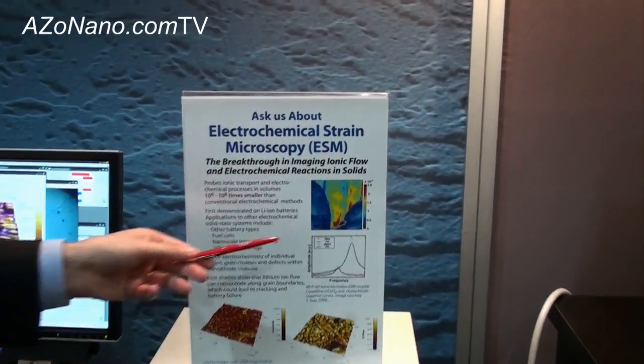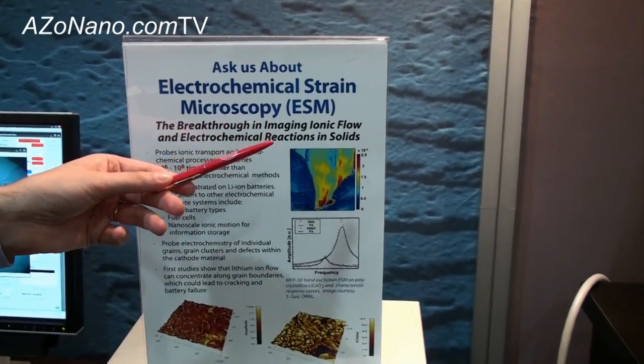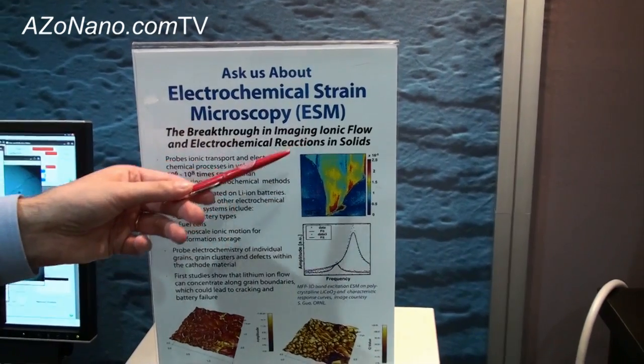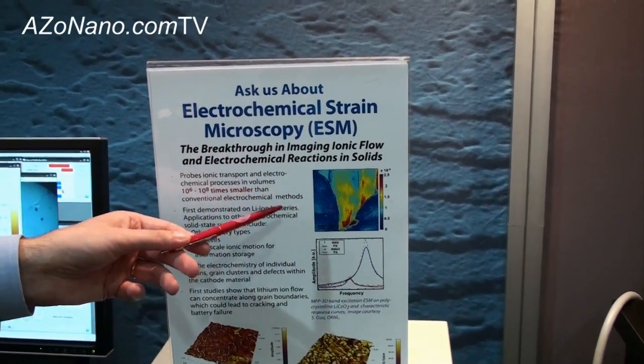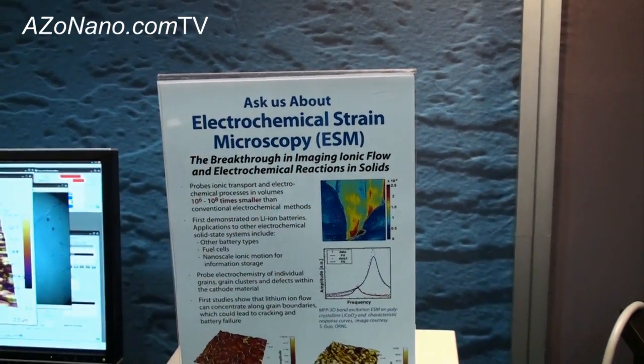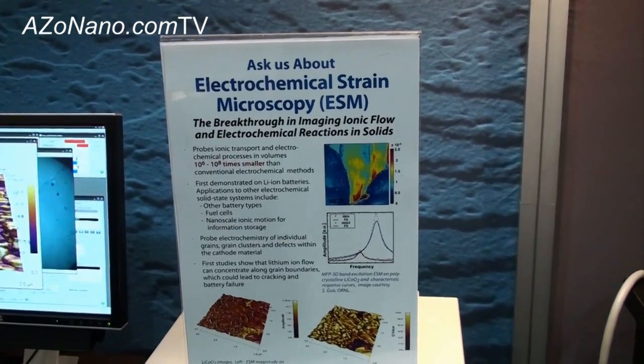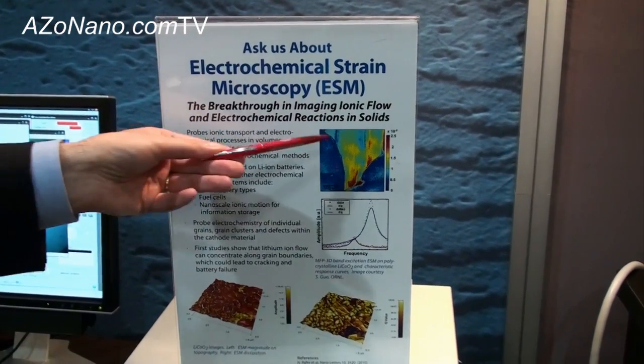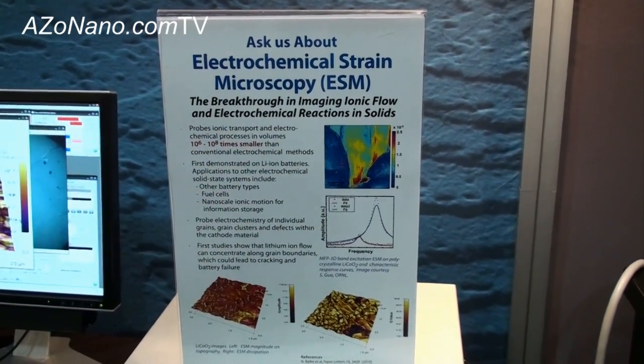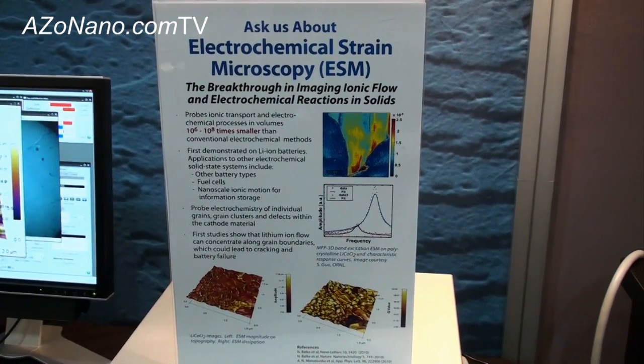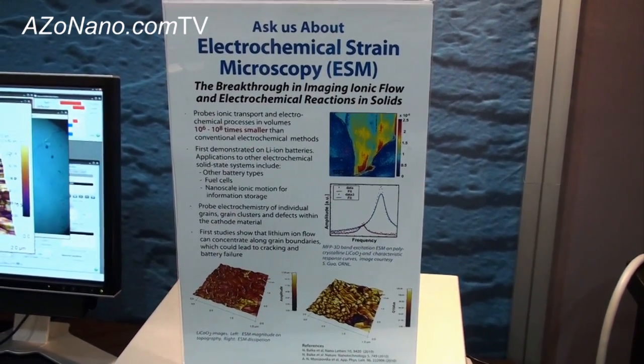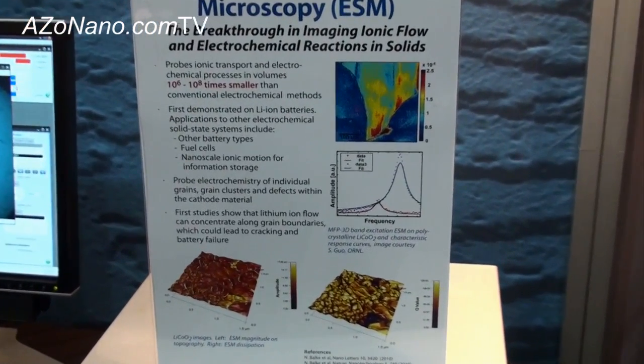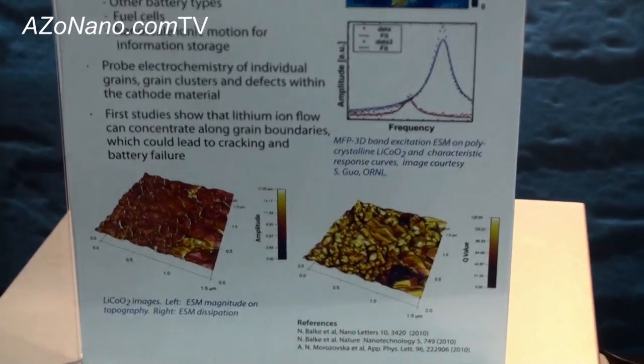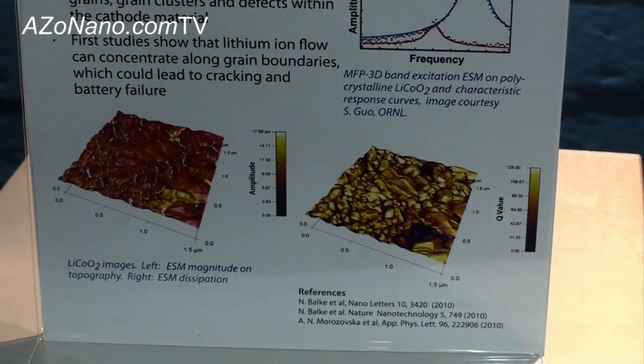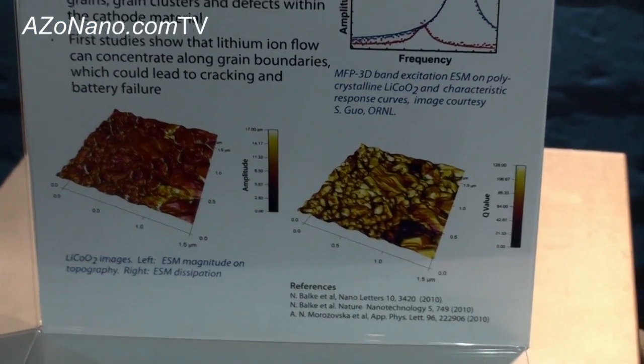So we have an example of the image where we have very strong electromechanical response in one grain, and we have no electromechanical response in the other grain. And this electrochemical response comes from lithium ions moving within this grain and not moving in this grain. What was even more wonderful for us is that we come to this meeting, and all of a sudden Roger and his merry men can make this technique work on the microscope right here. And I think Roger can talk about it more.